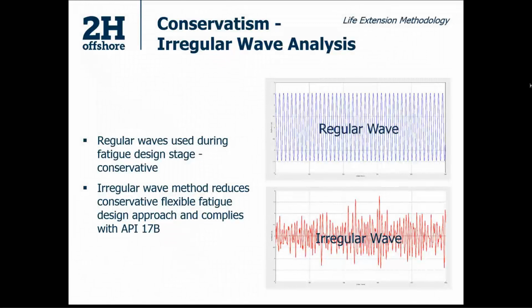It still represents the amount of energy that the riser would see in those conditions, in the predicted conditions. And we can also take measured conditions and generate irregular wave traces in order to calculate the damage that's been accrued. And I think what's important to note here is that the irregular wave method, even though it reduces conservatism, complies with the approach that's laid out in API 17B.